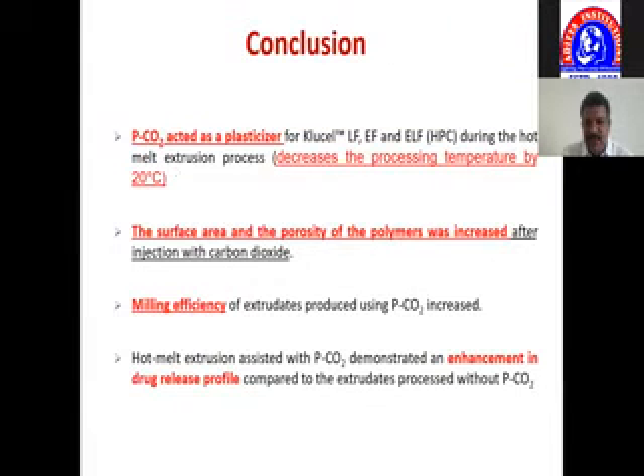So the conclusion is, carbon dioxide acts as a plasticizer and thereby reduces the processing condition by 20 degrees. The surface area and the porosity of the polymer were increased, and that is why you see enhanced dissolution. The other point also is that, once you compare without carbon dioxide and with carbon dioxide, the extrudate with carbon dioxide was very easy to mill. So the efficiency of milling was also improved.